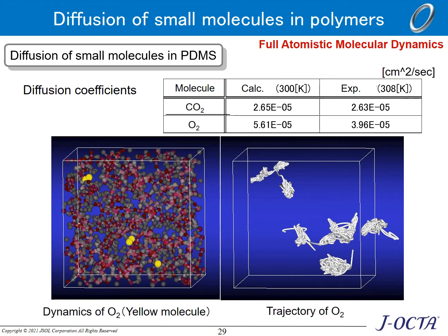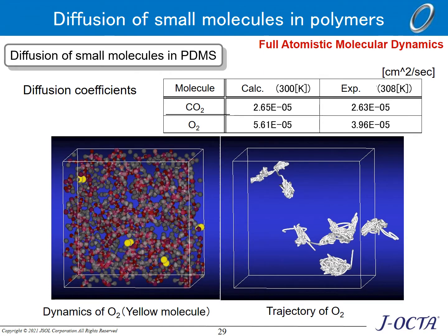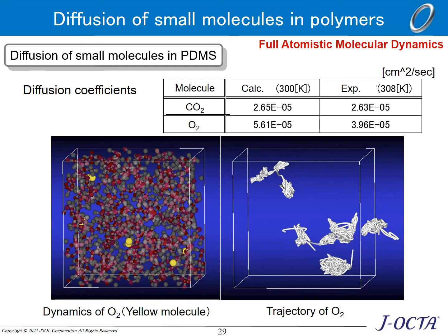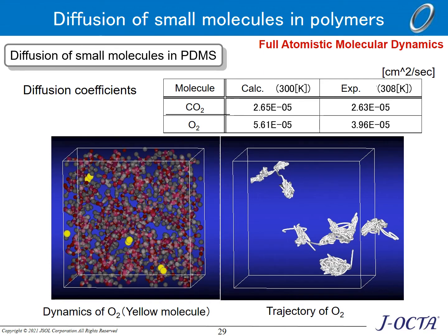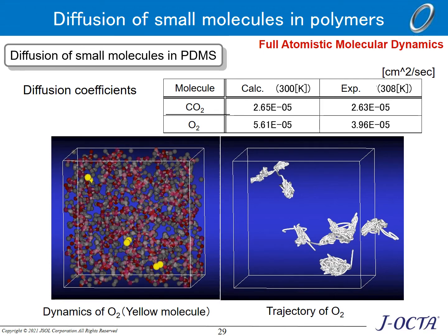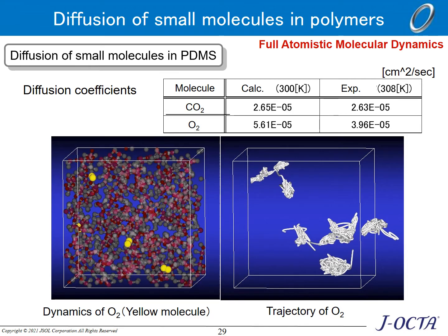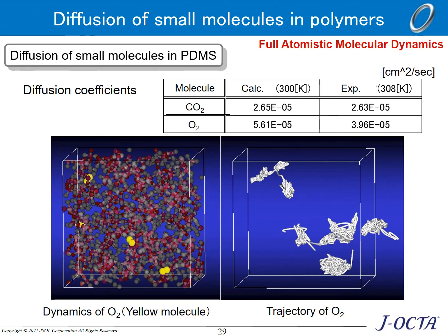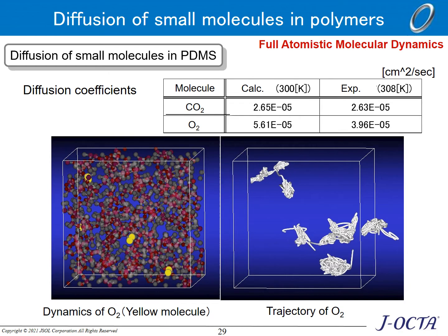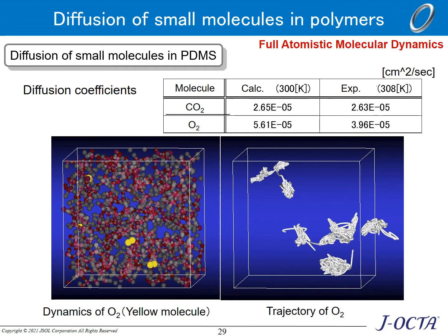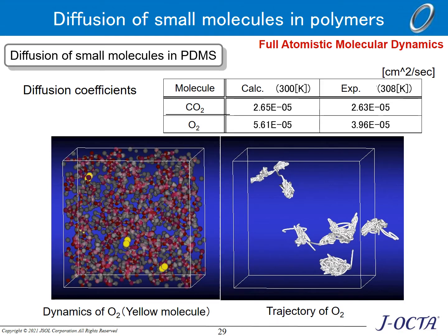The trajectory of the oxygen molecules is shown in the figure on the right. The resulting trajectory can be used to evaluate the self-diffusion coefficient. The upper table shows the self-diffusion coefficients of oxygen and carbon dioxide, both of which are in good agreement with the experimental results.